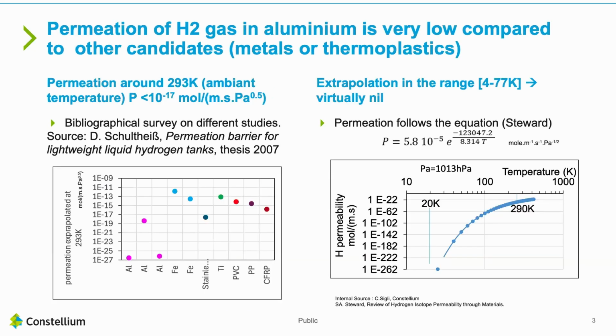So concerning permeation, here is a bibliographical survey conducted by David Schultheis. You can see different data gathered on permeation for aluminium in pink, steel and stainless steel in blue, and composite in the other color. You can see that at room temperature, the permeation of aluminium is very low. And if we make an extension with the Steward law to look at very low temperature, you can see a strong decrease of permeability. And at 20K, the operating temperature for a hydrogen tank, the permeation is virtually nil.